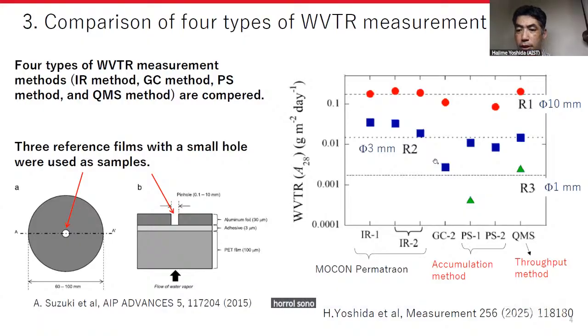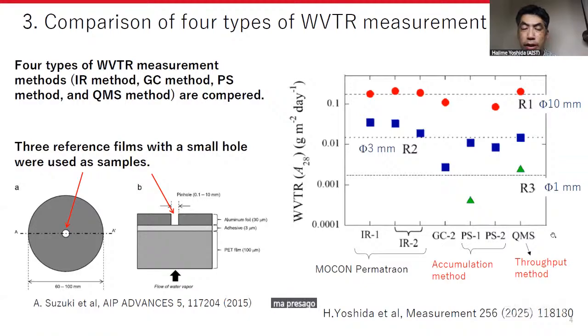As shown here, the result of the throughput method is close to the calculated values shown by the dotted lines, while the result of the accumulation method tended to be lower than the calculated value. I think this result shows the throughput method is more reliable than the accumulation method in the case of water vapor transmission rate measurement. Please go to the next slide.